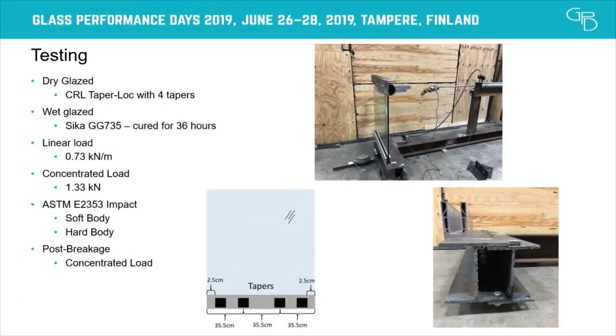So that was the easy part. Now we come to the testing, and it just went downhill from there. So we're looking at the dry glaze system, like I said, as well as the wet glaze system, the linear load, the concentrated load. For the dry glazed system, we had 4 taper locks, 4 places where it was held in place, and we followed the manufacturer's instructions of having at least 2.5 centimeters from the edge on both of these, and then the 2 middle ones were 35 centimeters centered.